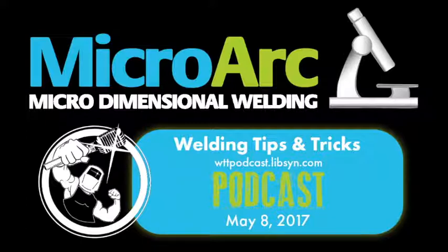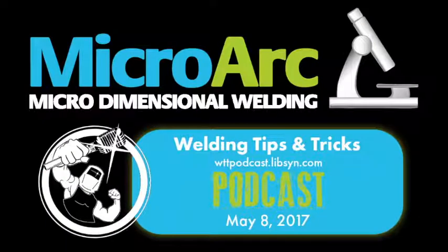So when we do it in the welding business, I use a carbide peen with a round nose. I have a pneumatic one, and I also have a manual one for bigger peening. It's a piece of carbide that's ground down with a certain special shape on it, in a round end. With a hammer and the peen, I'll counteract the pulling action of the weld, because the weld wants to contract, and the peening wants to push it back to where it was. So we do a lot with that. But you've got to be very careful with tool steel. When you're peening tool steel, you can crack it, you can break it, so it has to be hot. There's certain criteria that you have to follow, or you can make things worse. But that's part of the distortion management that we use, is peening.